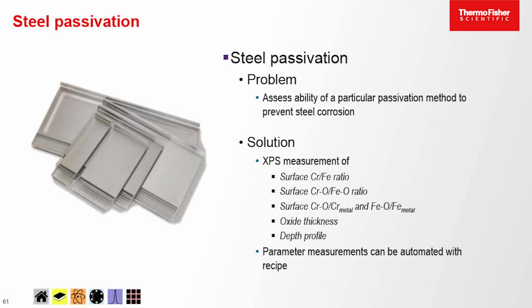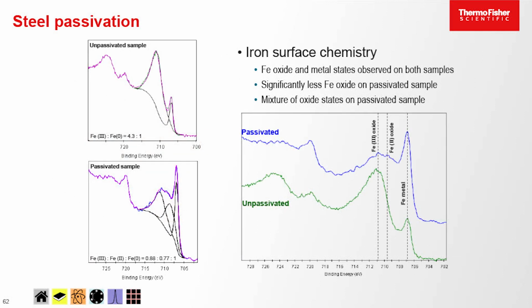But before we do that, let's look at something that's a bit more related to this in terms of trying to prevent corrosion, and how we can use XPS to understand steel passivation and issues that might come when it's not being done correctly. So what we want to really do is understand the formation of typically the enriched chromium oxide layer at the surface of the steel and determine if that is conforming to the amount that's supposed to be there. So if we look at the iron surface chemistry and we look at a passivated steel surface and an unpassivated steel surface, this is the peak for metallic iron, and this is the iron oxide peak.